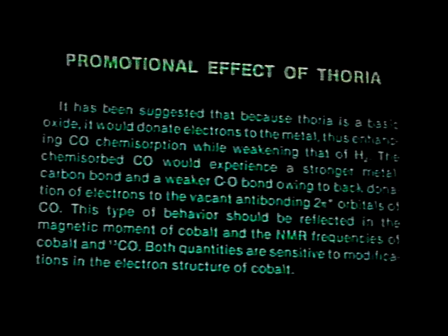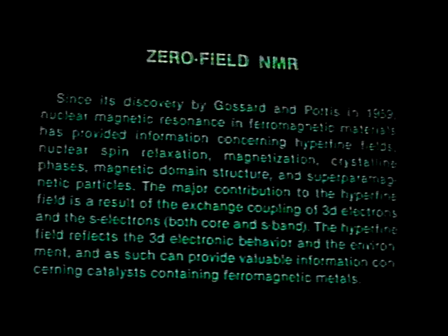and C13. Now, in the case of cobalt, since it is ferromagnetic, you cannot do a straightforward NMR. But what you do is to do the NMR of cobalt in its own magnetic field. It's similar to a Mossbauer experiment in iron, where you see the six-finger pattern splitting because of the internal field of iron. Now, cobalt has a similar internal field.